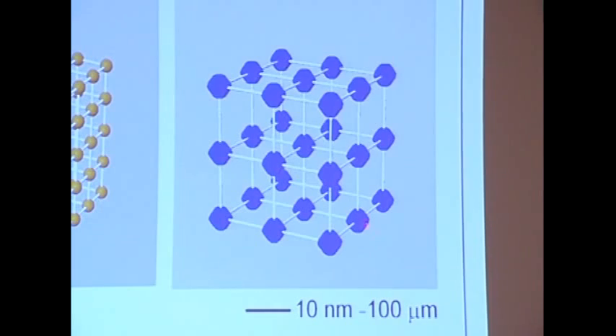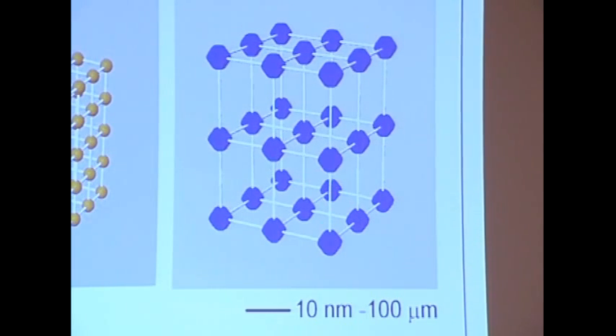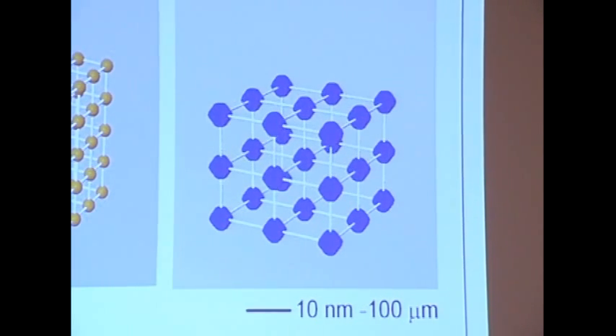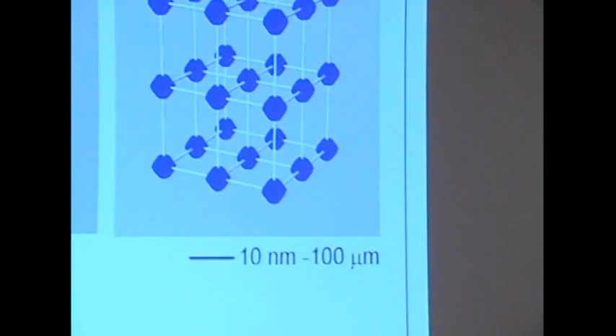In addition, you can put those meta-atoms into, for example, PDMS rubber, embedding quantum dots or something in the rubber. And you can achieve strain. You can stretch the rubber. You can extend the lattice size 100%. Now, if you look at lattice crystals like silicon or gallium arsenide, a 1% strain is huge. So that gives you a lot of possibility to tune the properties.